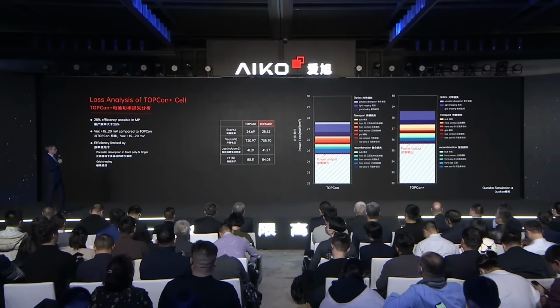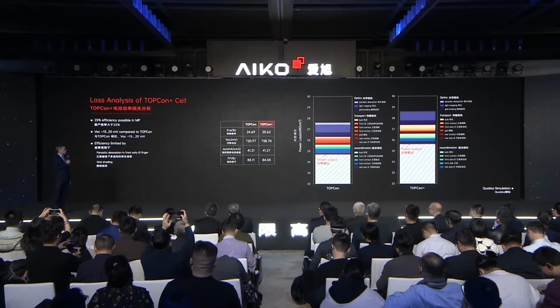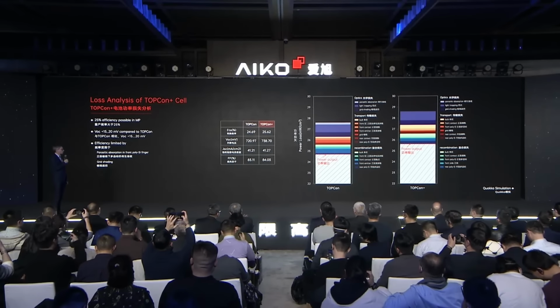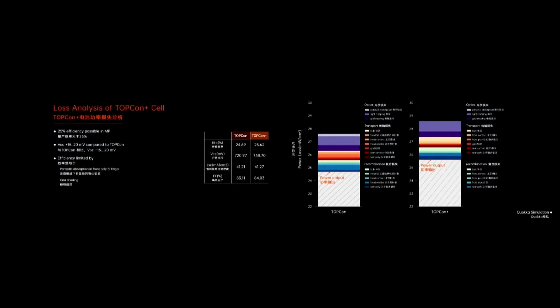upon this? And in 21, my former colleagues at Fraunhofer and me, we published a paper on the TOPCon cell, where we switched the material from N-type to P-type, and now we can omit the full area boron diffusion at the front side. Thereby we get a higher VOC, which translated also in a higher efficiency of up to 26%. And so I've simulated here a TOPCon Plus cell, which features polysilicon contacts both at the front side and the rear side, and these give us a boost in VOC to close to 740 millivolts. We also have improvement in fill factor.